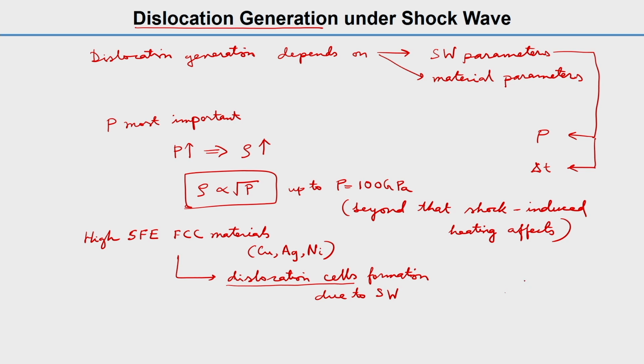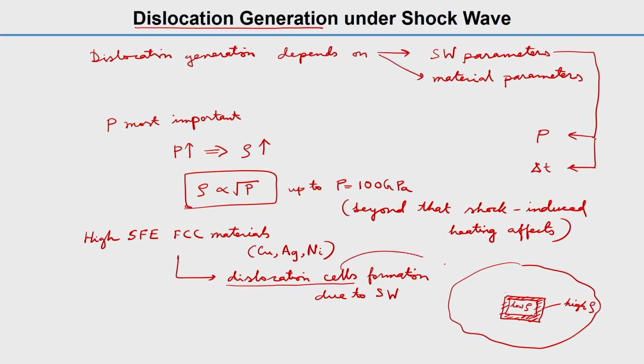So, what happens is in a material, in a grain, if this is a grain, there are some cells that will form where you have walls like this. Wall means this portion has high dislocation density, I would write high rho, that is dislocation density, and inside it has low dislocation density. So, there will be dislocations inside, but the density will be low. So, this is called a dislocation cell. Okay. So, this dislocation cell forms under shock wave, and this happens for these high stacking fault energy FCC materials, and